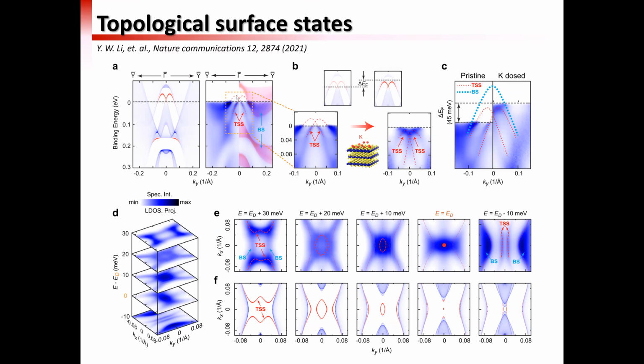So at the beginning, you can see in this area, if you can see my cursor, on the left-hand side is experiment, on the right-hand side is experiment overlapped with a calculation. And you can see clearly that in addition to the pretty broad bulk band, there's a pretty sharp dispersion here, which should be the topological surface state. But unfortunately, in the as-grown sample, the Fermi level is lower than the neutral one, so the Fermi level is lower than the Dirac point.